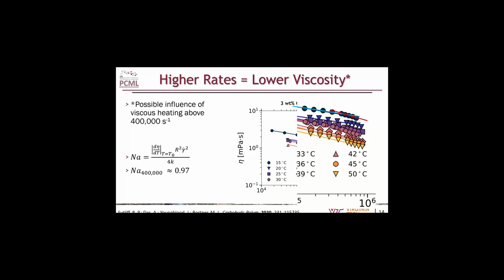What we get is right at about 400,000 reciprocal seconds, we have a Nahme number of 1. A Nahme number of 1 is sort of the cutoff of where you should be concerned about viscous heating effects. So by the time we get to our highest rate of 800,000 reciprocal seconds, we're looking at a Nahme number of about 3.9, showing we almost certainly have viscous heating effects.